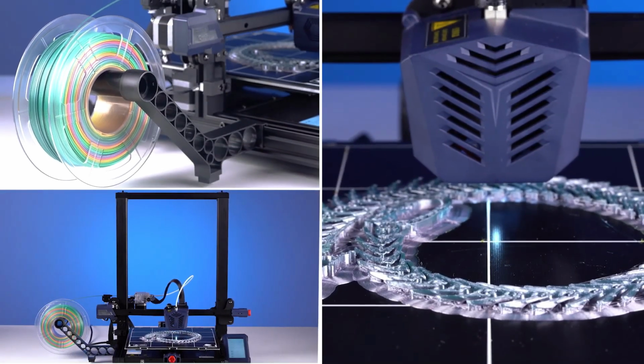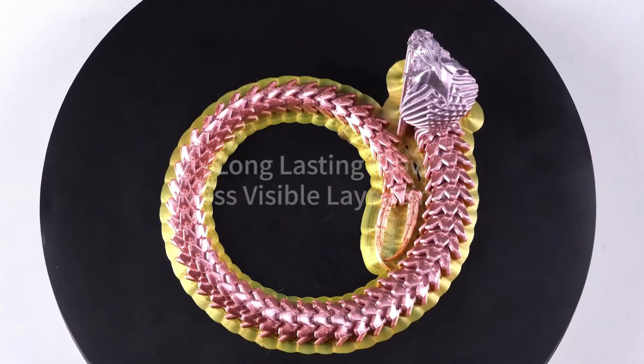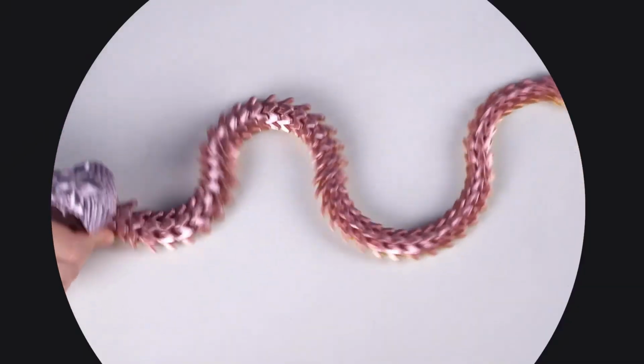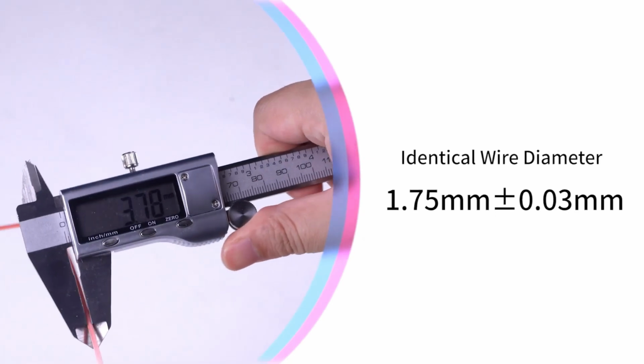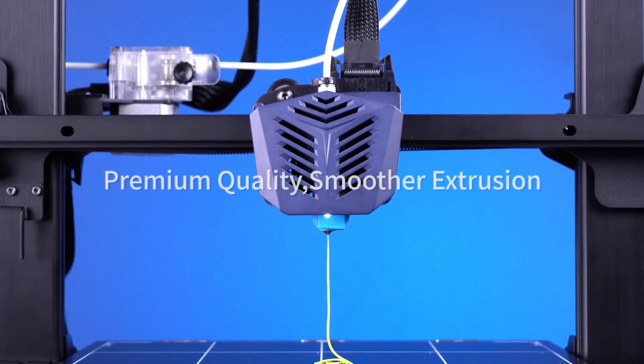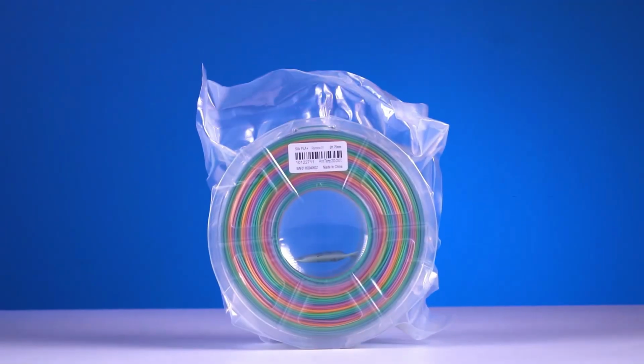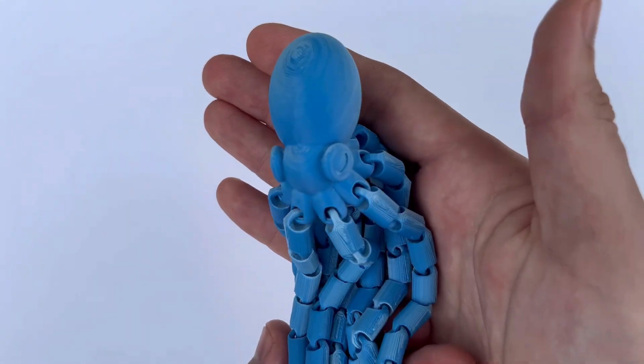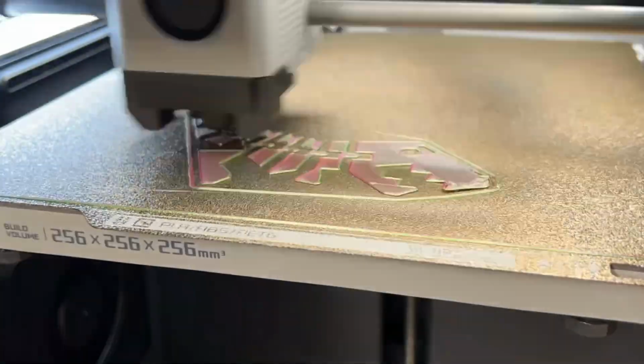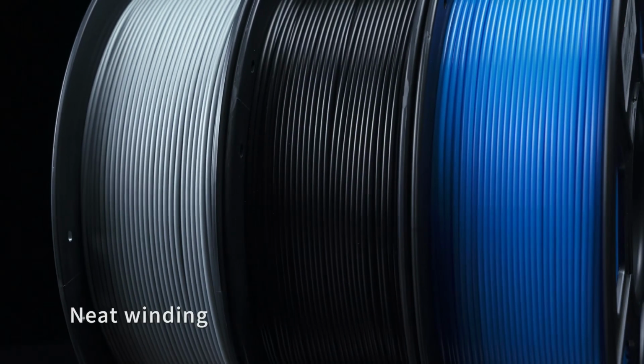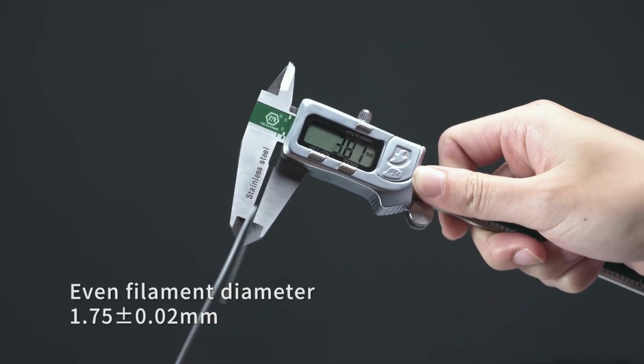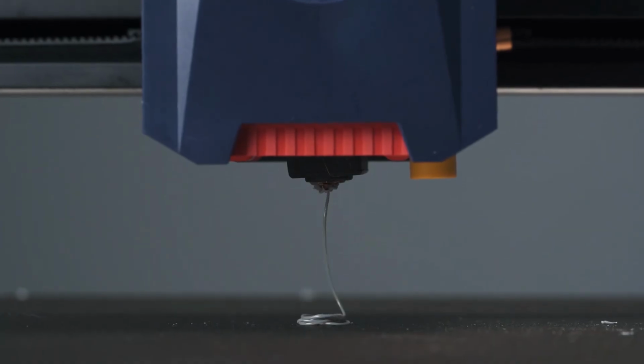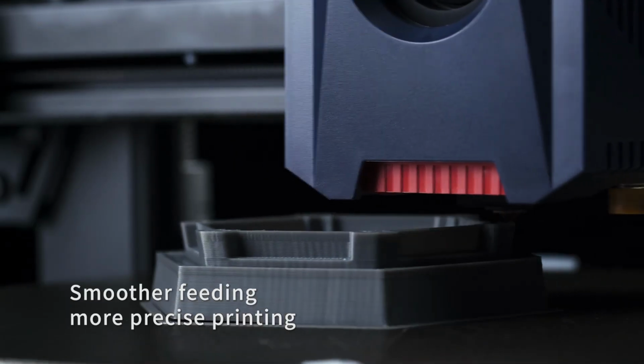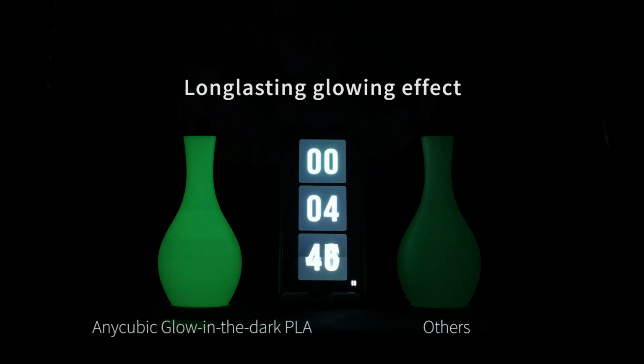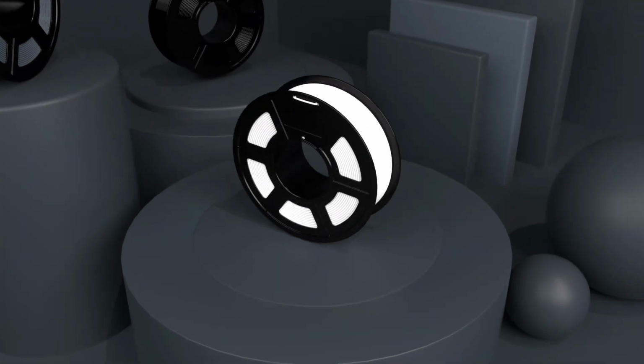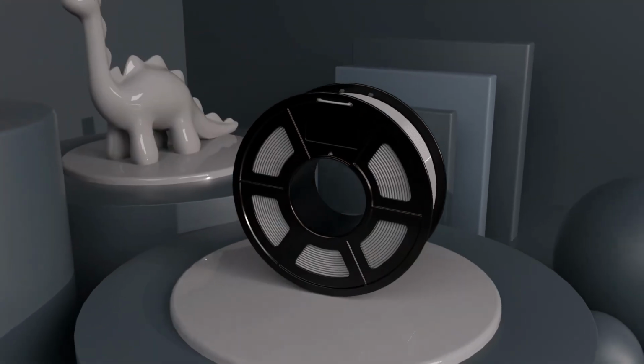And as far as mechanical properties between PLA versus PETG versus ASA, they vary significantly. PLA is hard and has a high degree of stiffness, making it ideal for parts requiring precision. However, it is more brittle and less impact resistant. PETG is tougher and more flexible than PLA, providing better impact resistance. It is ideal for parts that need to flex or absorb shock, such as clips or outdoor items. ASA is the toughest and most impact resistant of the three, making it suitable for functional parts that need to endure mechanical stress or impact. It is also more ductile, allowing it to flex rather than crack under pressure.